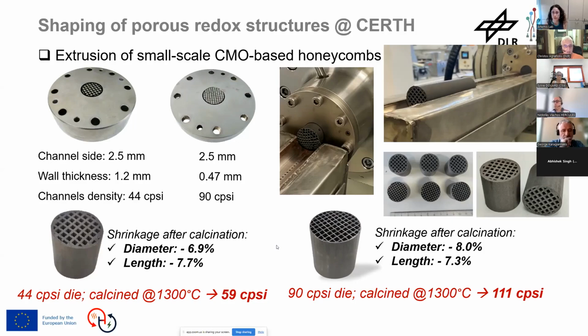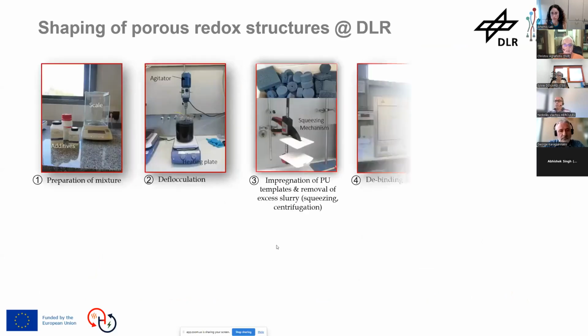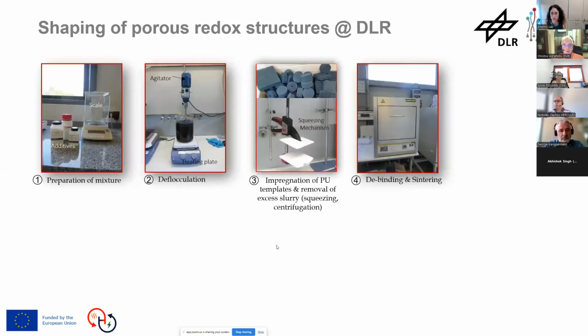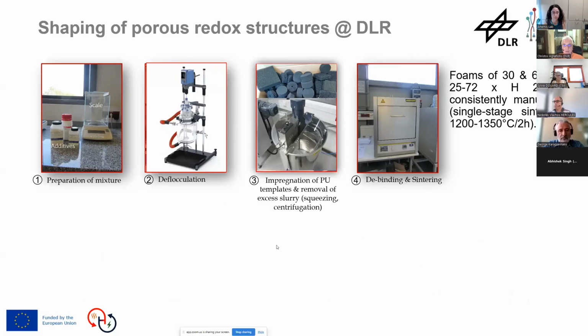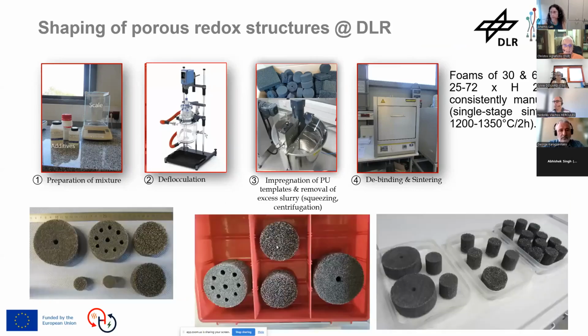So they can produce flawless sintered bodies of the desired compositions that can be very well characterized, and they are very robust to be tested later on. Ourselves, we also do porous foams. We cover with a slurry polyurethane templates, and then we sinter the template, and we can come up with structures like this, which have porosity in 3 dimensions.